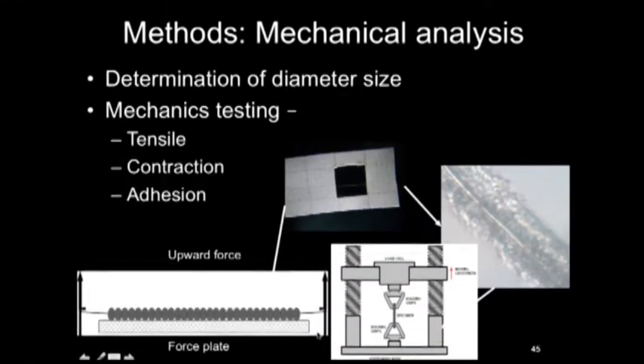And what we first did was measure adhesive properties as well as mechanical properties. We would take these threads, cut away part of the card, and press them down into a sensitive force plate, the same force plate we'd use for tensile testing. We'd press them down into the plate and then pull up on the force plate and measure the amount of force required to detach the silk. So it would be attached across these force plates, and that would make up about a 2 millimeter segment of these 10 millimeter thread segments.